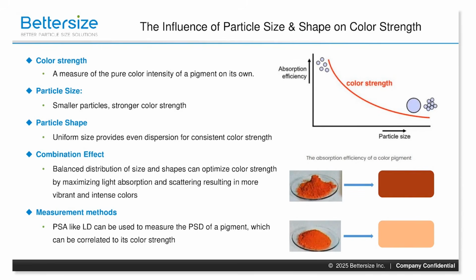Particle shape: spherical particles can provide a smooth and uniform dispersion, which helps in achieving consistent color strength. Irregularly shaped particles can scatter light in multiple directions, which can actually enhance the color strength. So, an ideal distribution is a well-balanced distribution of particle size and shapes, which can enhance color strength by maximizing light absorption and scattering and result in more vibrant and intense colors. Particle size analyzers like laser diffraction can be used to measure the particle size distribution of a pigment, which can then be correlated to its color strength.